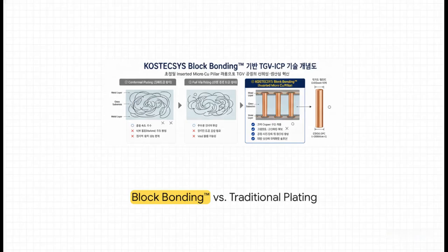The real magic trick here relies on a concept they call block bonding. Basically, they are bypassing that incredibly slow, highly risky plating process entirely. Instead of chemically trying to grow copper inside a glass hole and just crossing their fingers that there are no voids, they precisely insert high-quality, pre-made, perfectly flat copper pillars directly into the glass vias en masse.